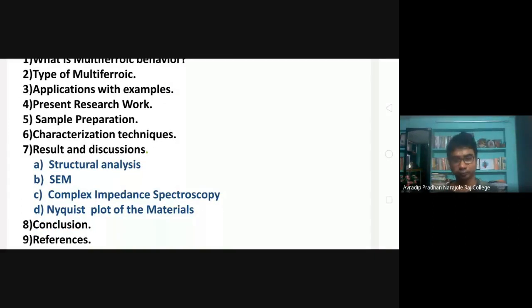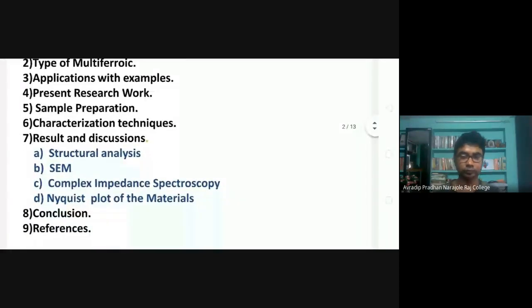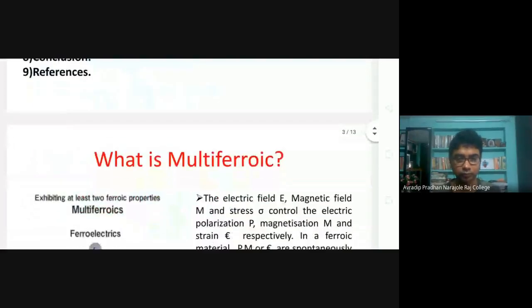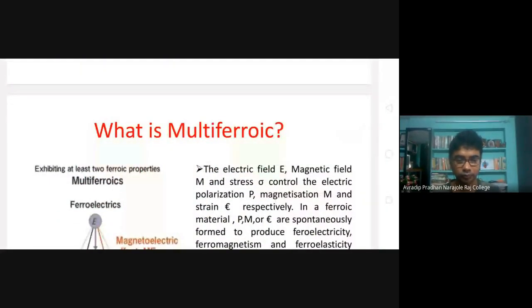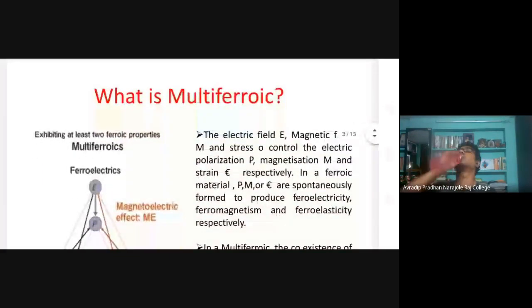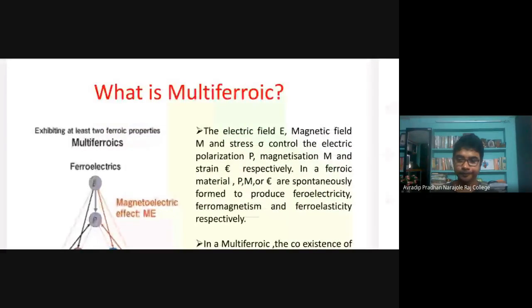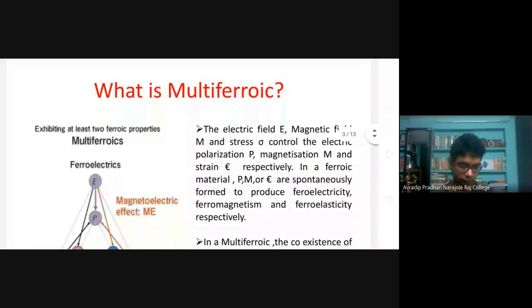In the results and discussion, four items are shown in the next slide: structural analysis, scanning electron microscope analysis, complex impedance spectroscopy, and the Nyquist plot of this material. In this particular work, I showed the good multiferroic property which I mentioned in my title: good magnetization and good polarization are present, and also a high dielectric constant with a low dielectric loss or tangent loss. Then I want to say what multiferroic is.